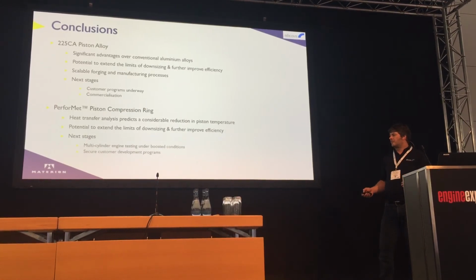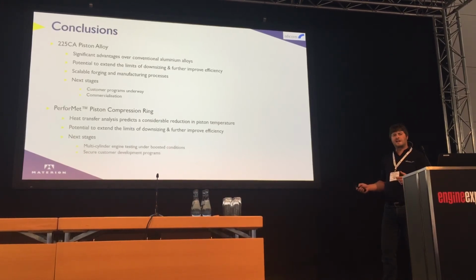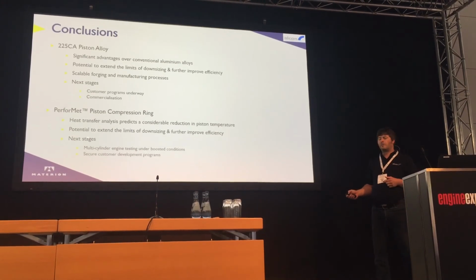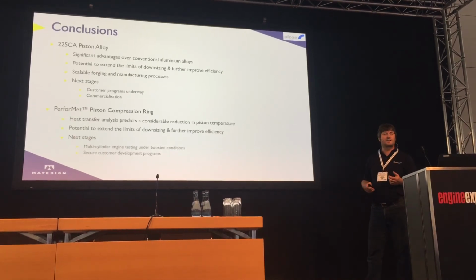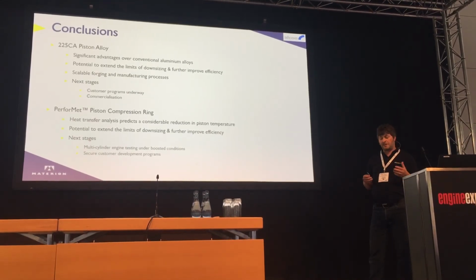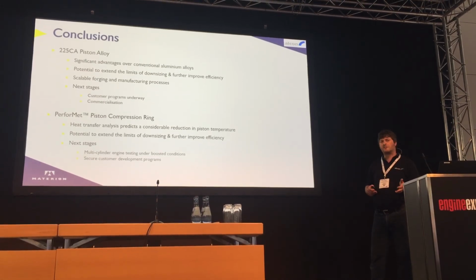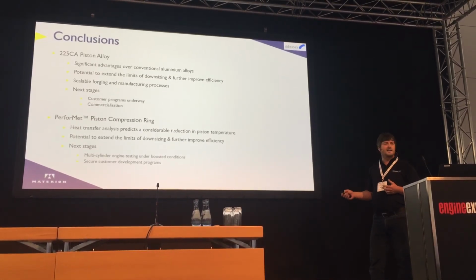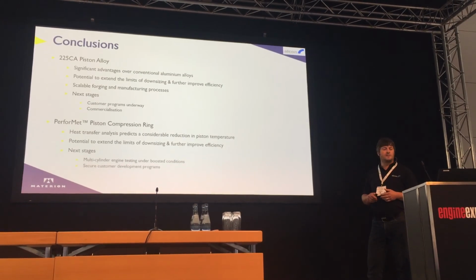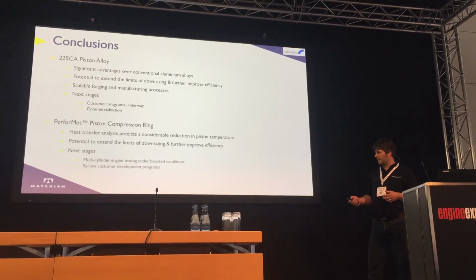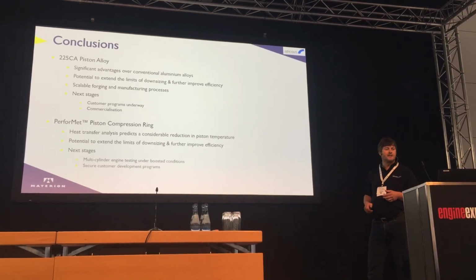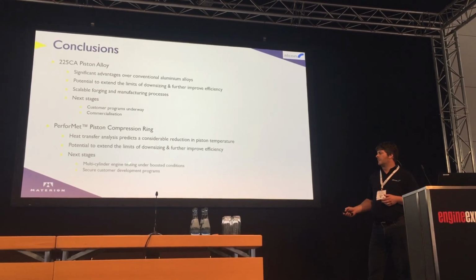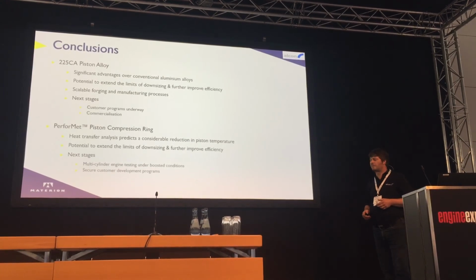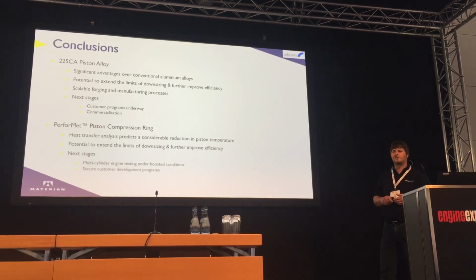The compression ring is still at an earlier stage of development, but again some really interesting results from the analysis and some of the tests that we did. And what we're now carrying out is some multi-cylinder testing. We have some pistons which are thermocoupled, and we're running some thermocouple tests to correlate the analysis work we did. If that correlates, we then go on to doing some BSFC measurements and some drive cycle work. And again, this is with an OEM. And that pretty much wraps up my presentation.